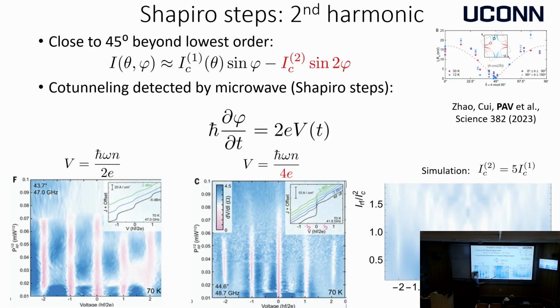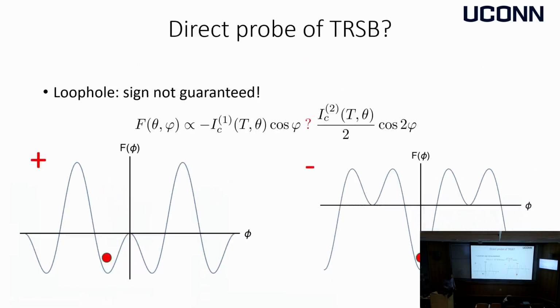Those signatures are quite smeared. But if you do the actual simulation, you notice that even if the second harmonic current is 5 times larger than the first one, those half steps are indeed quite a bit smeared, especially in presence of noise that's inevitably present in an experimental setup. So it's quite consistent with the second harmonic being present and maybe even dominant, close to 45 degrees. But that doesn't quite tell you that time reversal symmetry is broken.